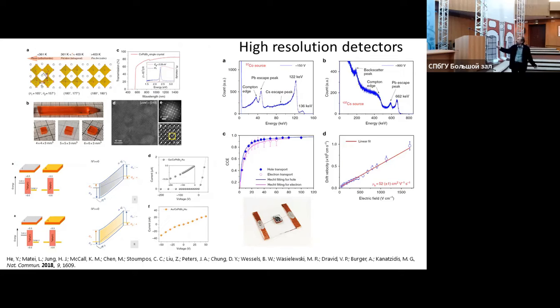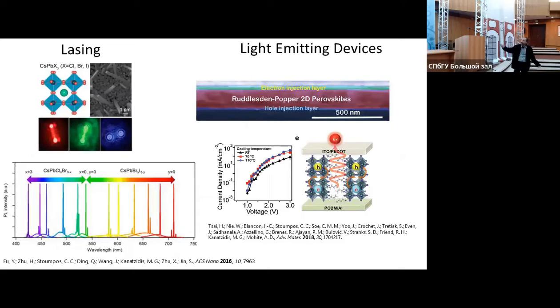That's one example. Another example of why these materials can be useful is this type of microwire I showed you before. These microwires can lase by themselves, and they can lase at a selected wavelength that you can fine-tune by the chemical composition. These crystals have a very special property. They have very parallel faces that act as mirrors, and thus they can lase by themselves. Unfortunately, not for a very long time, but that's something that perhaps we can fix later on.